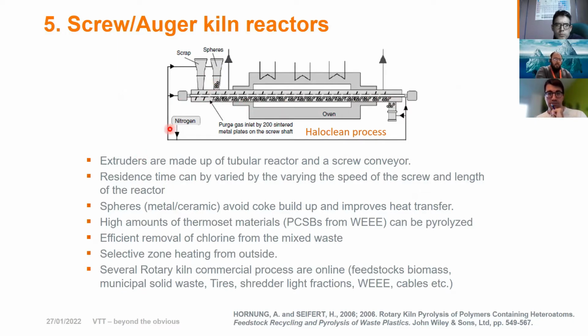In this particular case, the spheres are used in this Haloclean process to avoid any buildup of coke and improve the heat transfer, because they are hot and they are removing any fused plastics on the metal surfaces, and they are just collected here and then recycled back. This system has been used for thermoset materials, for example, printed circuit boards from electronic waste. It has been pyrolyzed in this type of system, and they have used this system for efficient removal of chlorine from mixed waste.